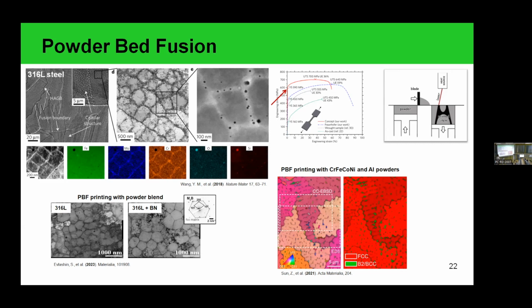these materials. And in the work we present here, austenitic steels were alloyed with boron nitrides, and you see the new phases form around these cells. Another work also demonstrated the possibility of in situ printing with the powders of the 4-component system and aluminum, and then the secondary phase is absorbed on these cell boundaries.